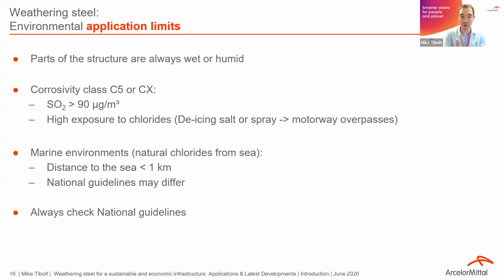And also if parts of the bridges are exposed to chlorides, like de-icing salt or spray, for instance, for bridges with motorway overpasses, because then the beams, or the steel in general, could lie in the spray of the de-icing salt of the cars and trucks. In marine environments, you have the natural chlorides from the sea. For a distance below 1 kilometer away from the sea, you should not use it. Of course, the national guidelines may differ depending on which sea we are talking about, if it's the Mediterranean, the North Sea, or the Baltic Sea. And anyway, it is always recommended to check the national guidelines if there are specific limits which are formulated.